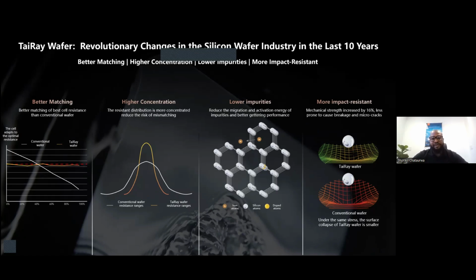Then the last one, which is very important, is more impact resistance. Actually, we strengthened the wafer. So our wafer is stronger. It actually resists mechanical strength by increasing it by 16%, which is less prone to cause breakages and also micro cracks during transportation, during installation, and also during just merely handling of modules.